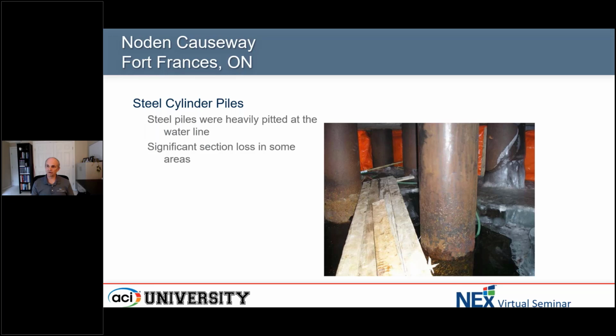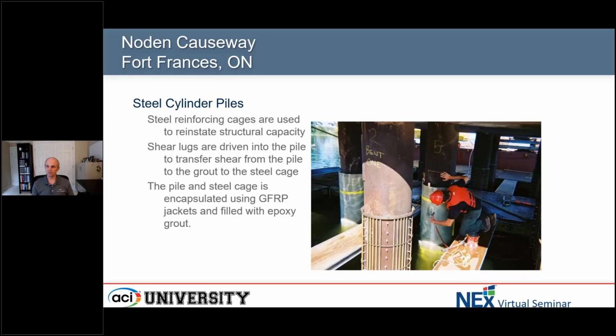So the repair of these structures involved FRP encapsulation, but because of the severity of the pitting corrosion, there was a structural remediation as well. The structural remediation entailed putting basically high-strength steel rods and steel cages around the existing steel piles, along with some shear lugs that were driven into the face of the steel pile to create bond between the steel cage and the existing pile, to allow some stress transfer between the steel cage and the existing pile. So you can see that in the photo there.